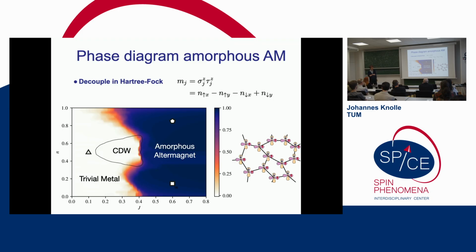Oh, the whole lattice structure, the whole crystal structure. Yeah. Sorry, how do you physically avoid the spin glass in this case? Oh, yes. So the spin glass we do avoid because we have two orbitals per site and so on. And so there is no frustration. So if you want, it's like a hidden ferromagnet. So the spin glass would come basically from a frustration if you have an antiferromagnetic interaction.